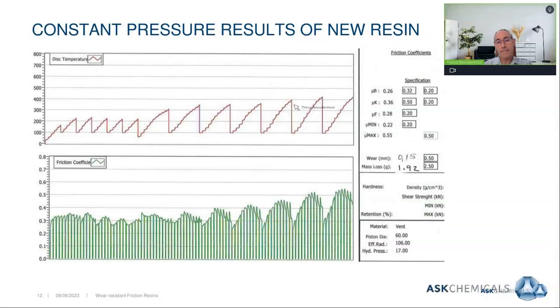Every time as the temperature increases, the friction coefficient is held very well up to the end of the application. This means that with this new technology, it shows a marked improvement in fade resistance as well, with the corresponding friction coefficients again on the right hand side.